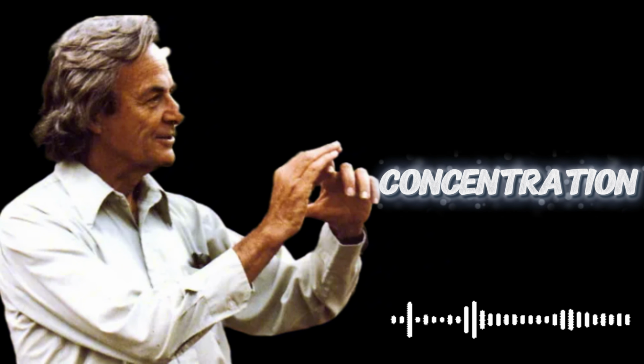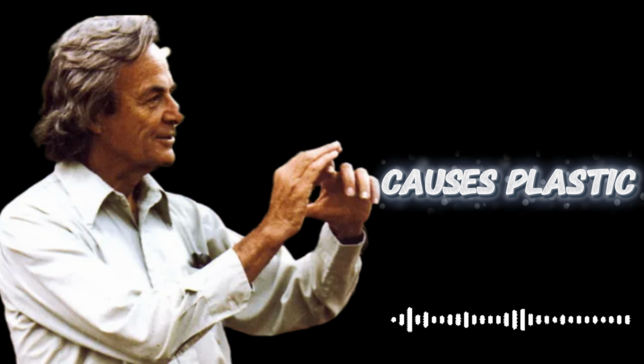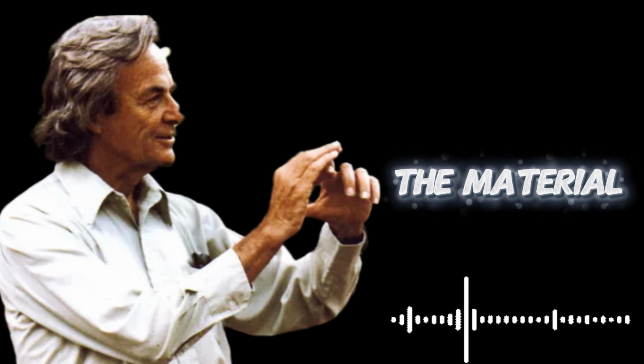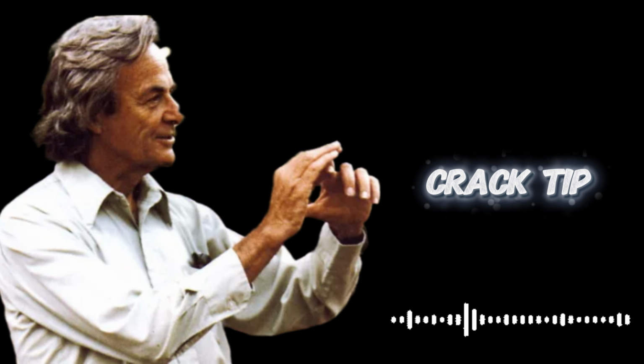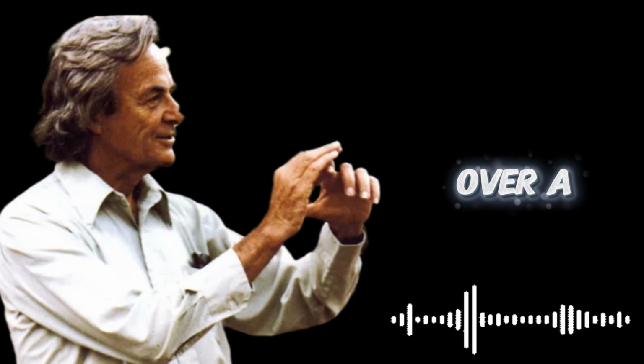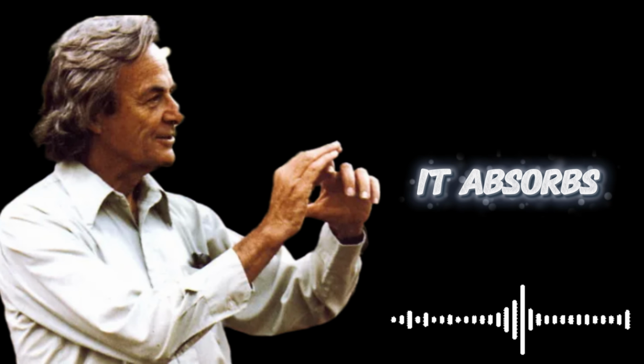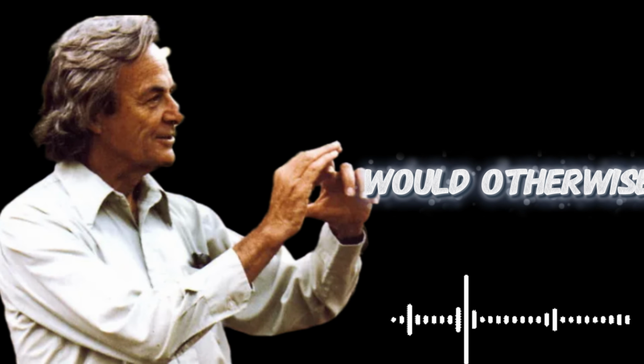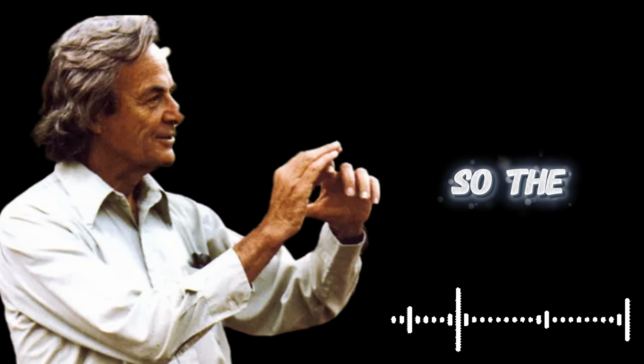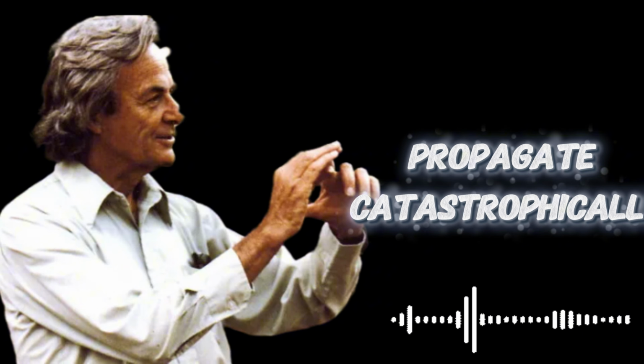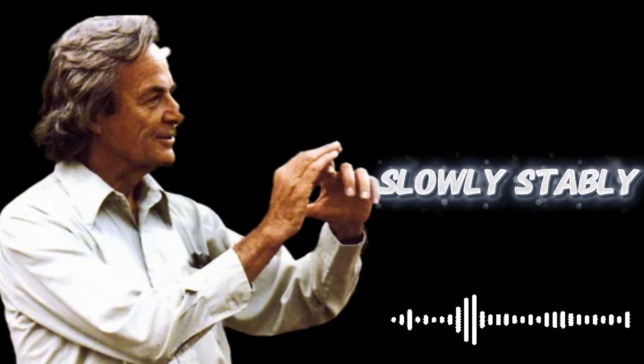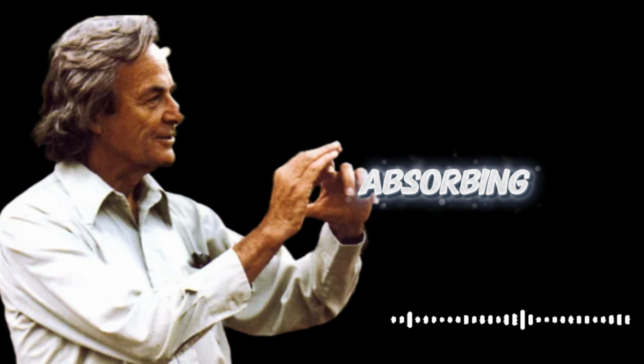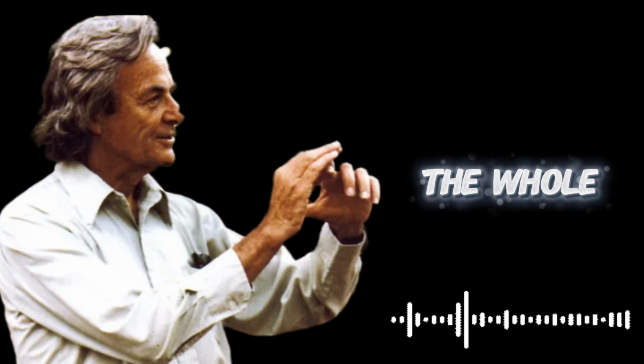When a crack tries to grow in metal, the stress concentration at the crack tip causes plastic deformation. The material yields locally. That yielding blunts the crack tip. It distributes the stress over a larger volume. It absorbs the elastic energy that would otherwise drive the crack forward. So the crack doesn't propagate catastrophically. It grows slowly, stably, absorbing energy through plastic deformation the whole way.